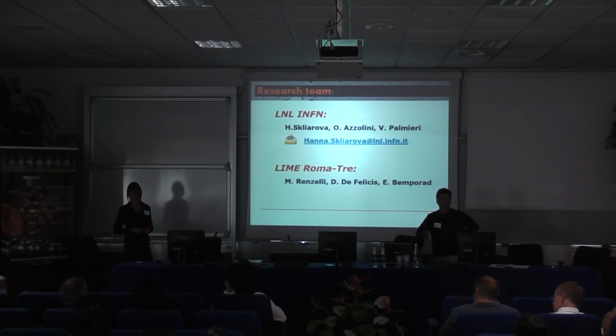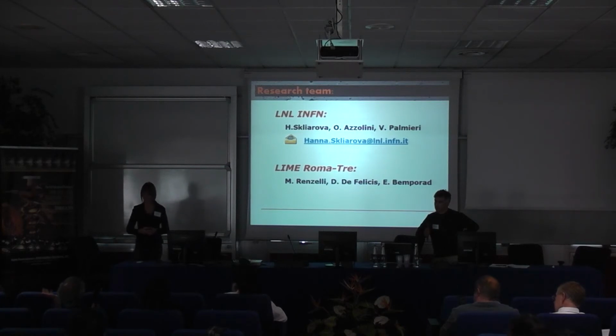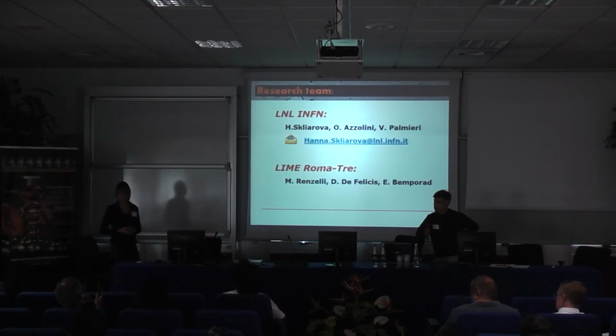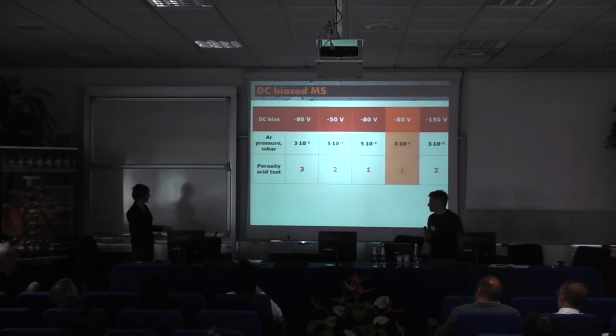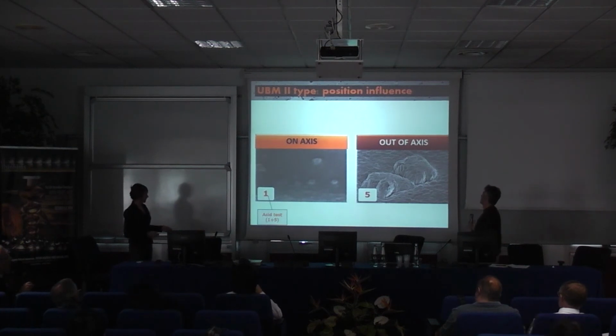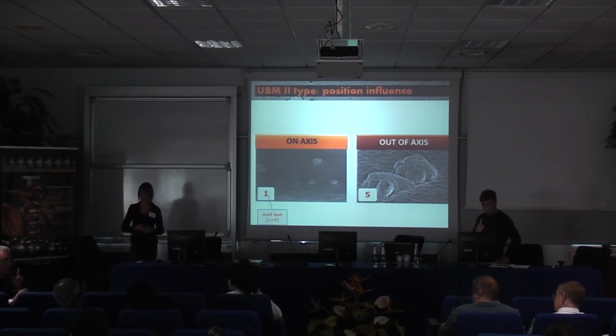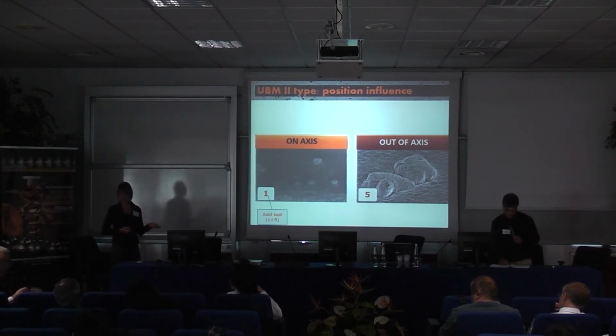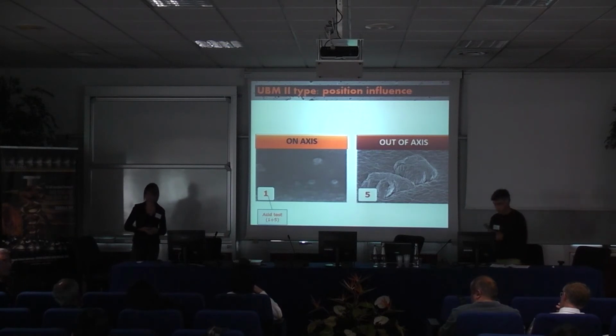I have a comment based on what you just said. When you did the experiment with a sample directly in line with the plume and one that was on the side, the one on the side was far more porous than the one directly in the plume. If there are such neutral microparticles, their proportion would be much higher on the side than directly in the plume, which would be consistent with your hypothesis. I think so. We have seen macroparticles, which I have shown here, and according to the EDX measurements, they are just niobium. If I understand, you mean there is not only the action of plasma washing, but also the amount of particles arriving at the other sample. Yes, absolutely agree. Thanks for the comment.